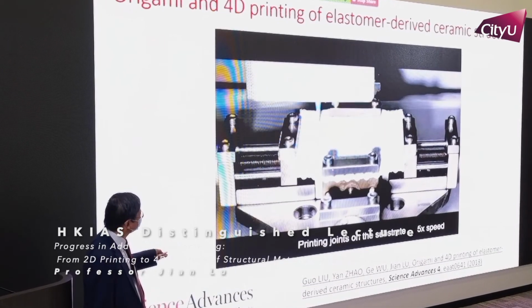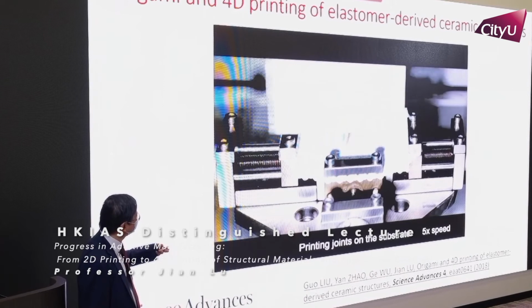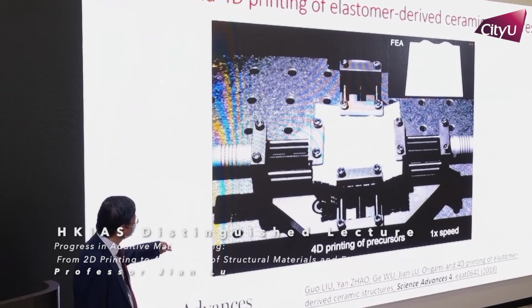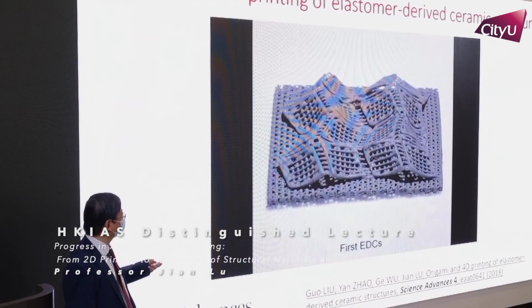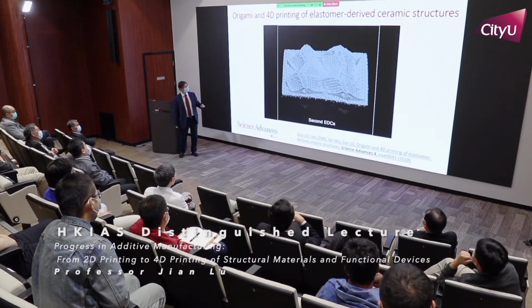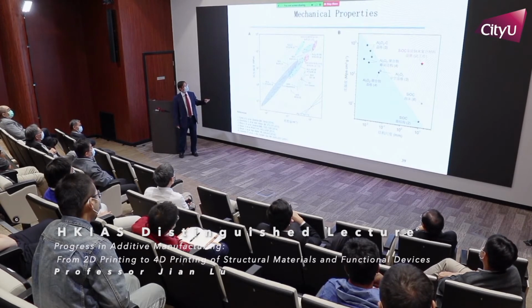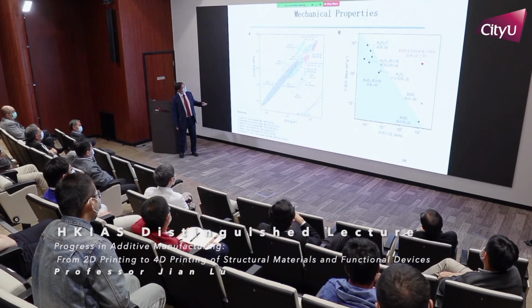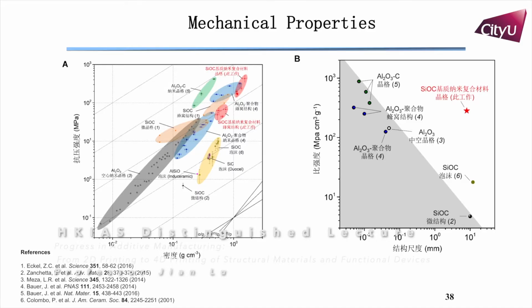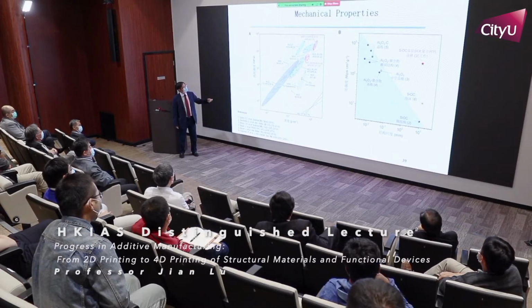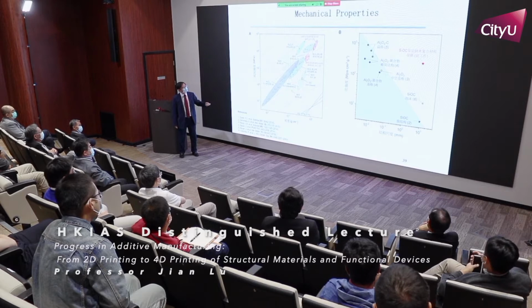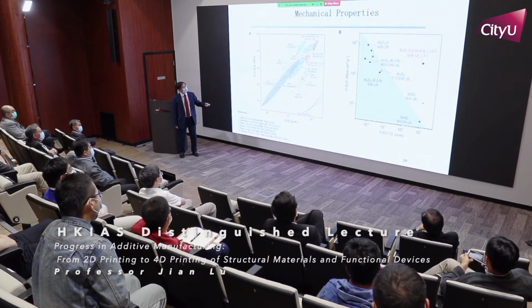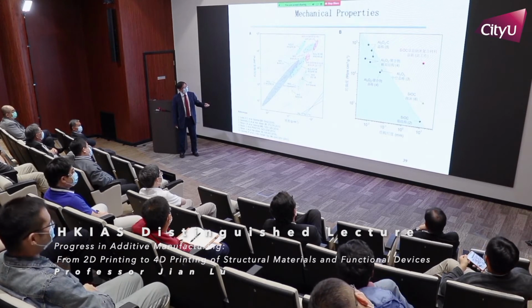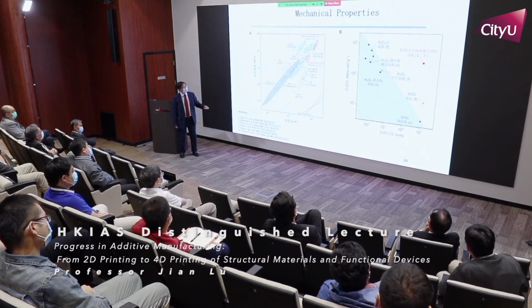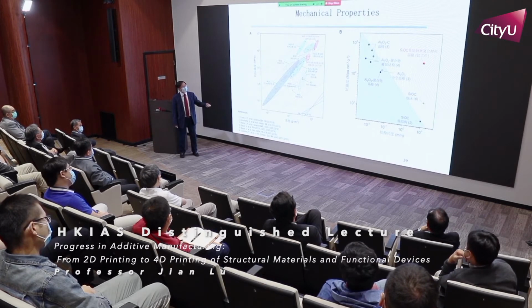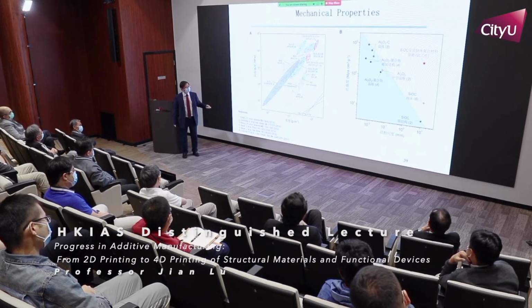As you may see, if it's bi-axial, we can generate many types. When you relax this, you can obtain many combinations of the structure. So for the ceramics, but how about the mechanical property? This mechanical property, sorry, is in Chinese and English. Okay, you can see here our mechanical property is quite good, especially compared to 3D printed ceramics. For the same specific strength, our size is 1 to 3 orders larger. We can even print an even larger structure. Okay.